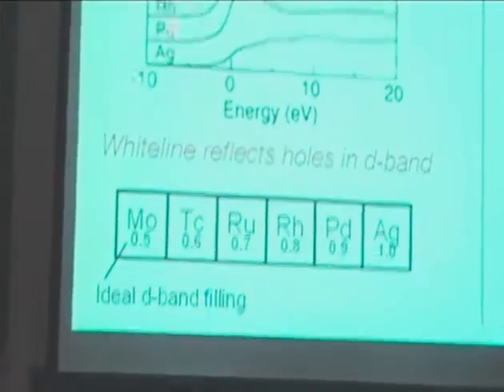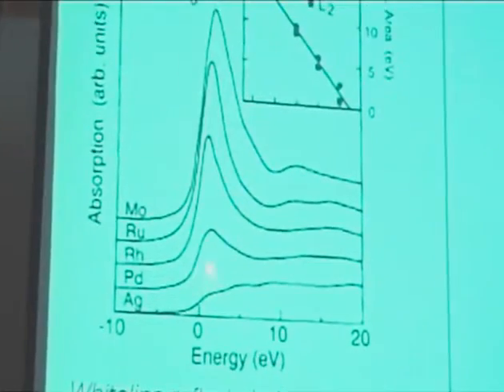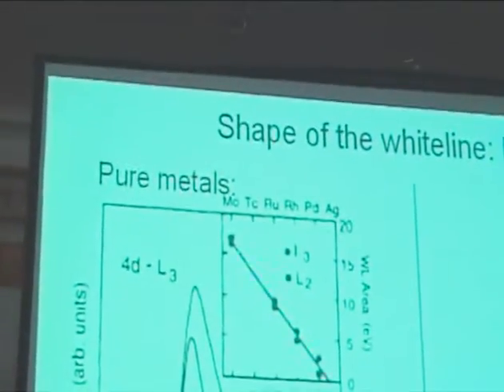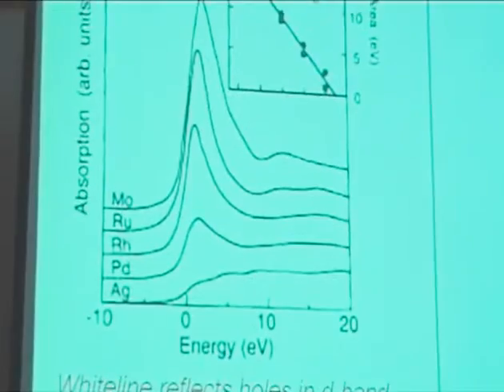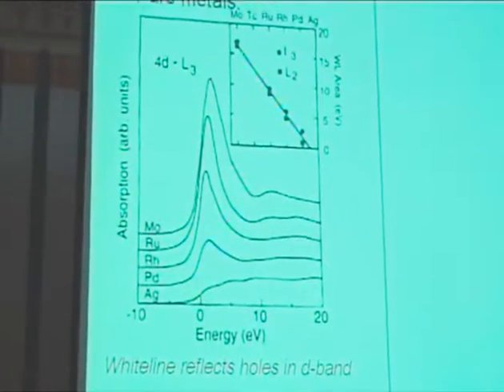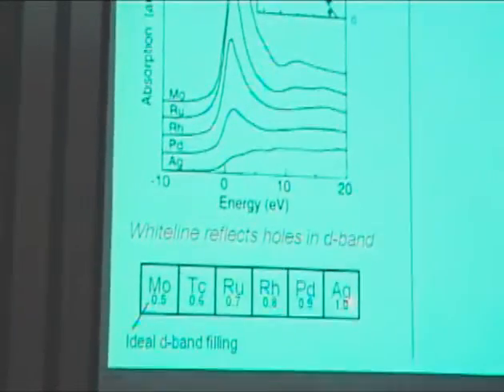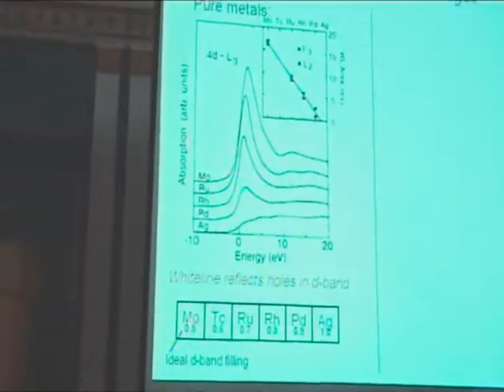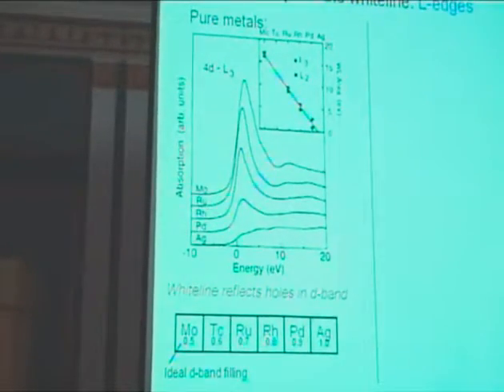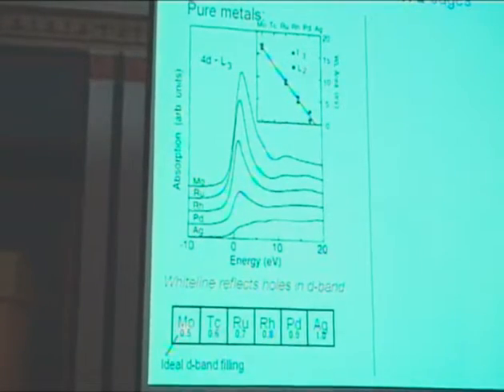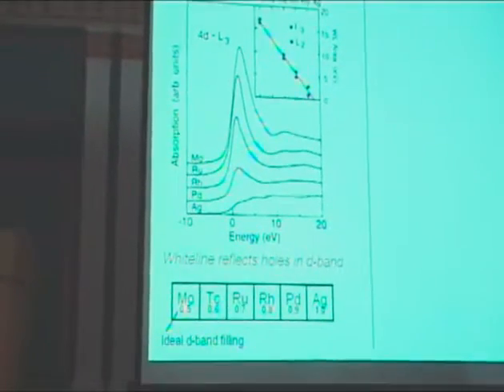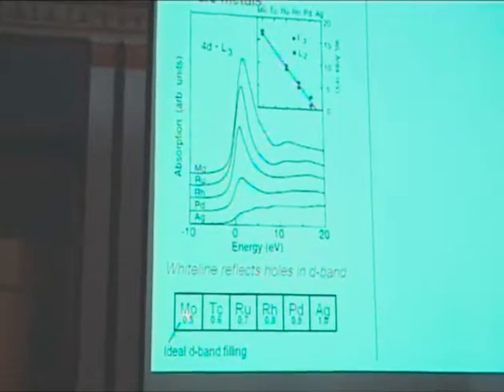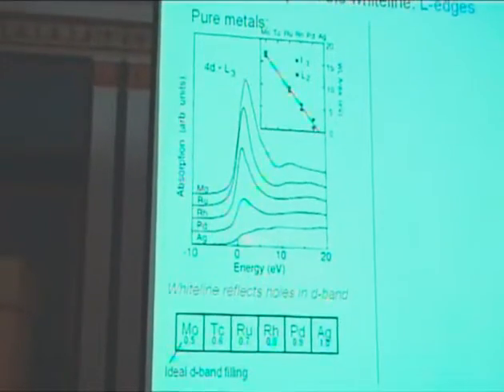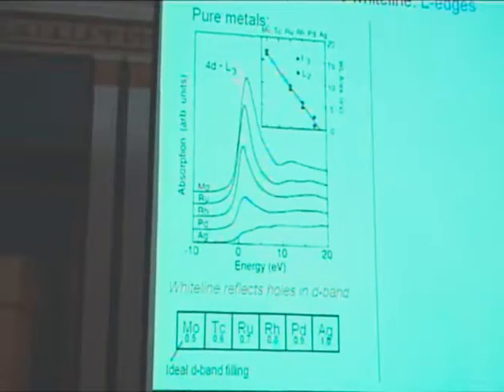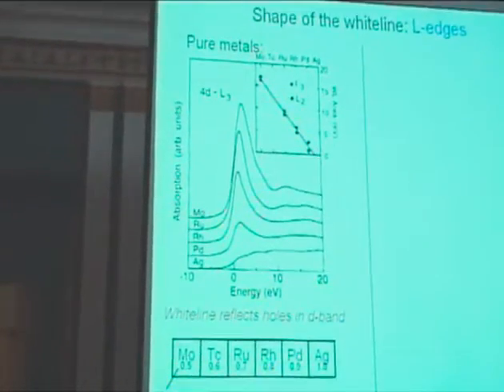For instance, many metals do it. Also the 4d series, silver, palladium, and so on to molybdenum. The more you go to the left in the periodic table, here you see it, silver going to the left to molybdenum. In silver, the d band is full. In molybdenum, it's half full. So here, you can go from the 2p to, in this case, the 4d, and you have the highest chance of doing it, because here are more holes than here, and that's what you see. Silver has no white line, palladium has one, and molybdenum has the strongest.